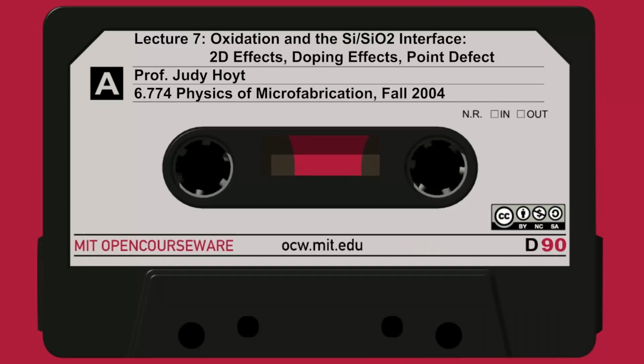So I have 2 oxides, both the same thickness, grown at different temperatures. They look the same, but they're not exactly the same. The intrinsic stress in this 1100 degree C oxide is going to be less than the intrinsic stress in this 800 degree oxide, because at a higher temperature, the oxide can flow more. There isn't as much built-in stress. Okay, so you say, well, this is under more stress than that.